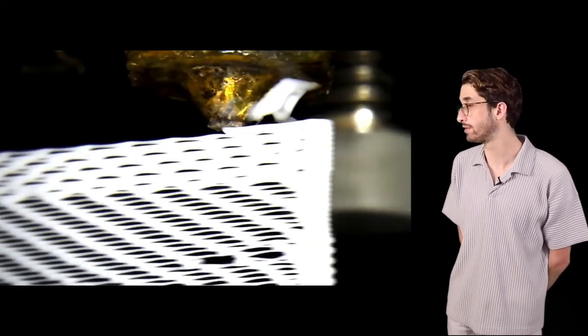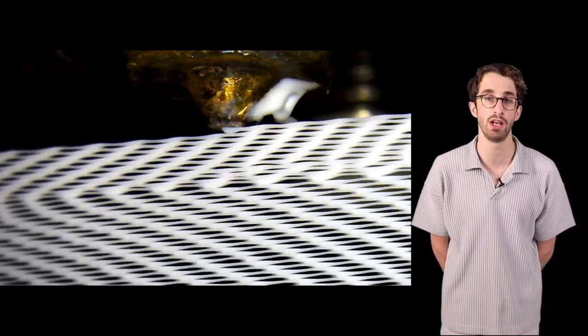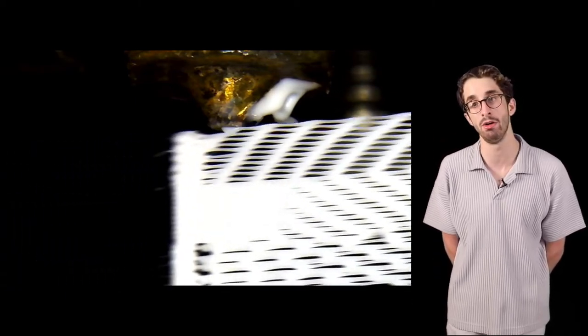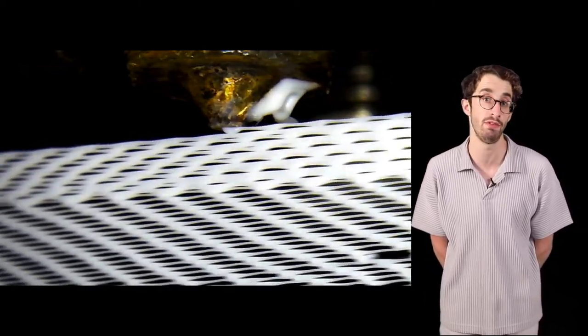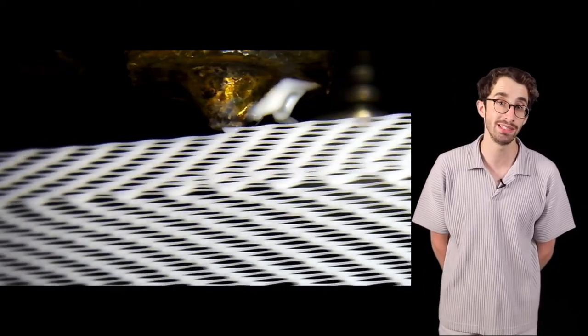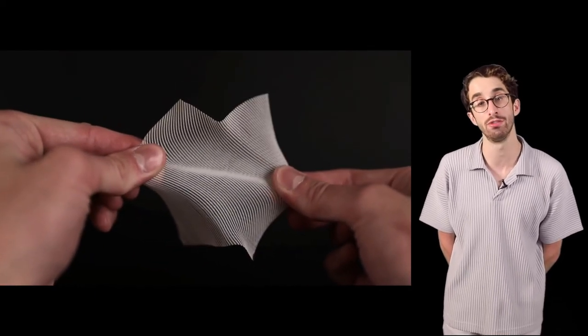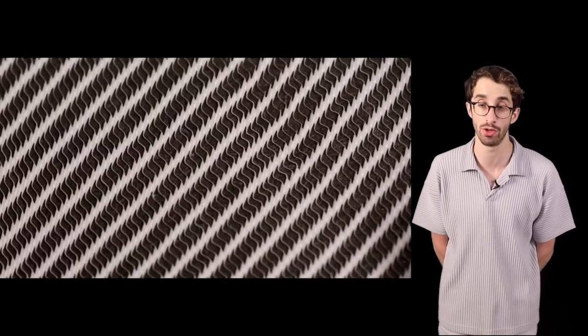Here's an up close of the printing process. Essentially, as the nozzle moves, a glob of thermoplastic builds up on the tip. This glob will snag the top of a pillar and be connected to the next one with a fine strand. As you can see, these fine strands enable the in-plane bending, which affords the flexibility and also the stretchability.